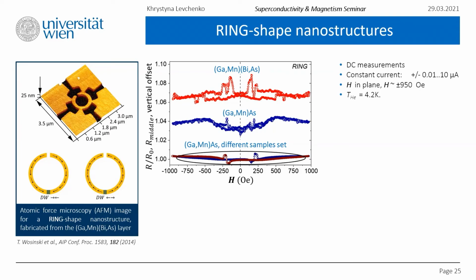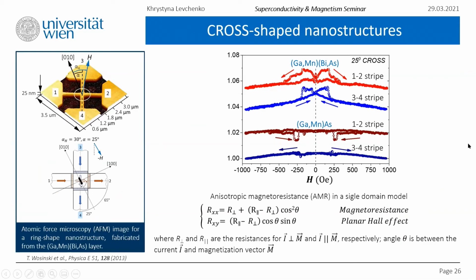So we wanted to have a large difference in the cases of low and high resistance, because the state of low resistance can be set as a 0, and the state of high resistance can be set as a 1. If we are having such a magnetic memory-like structure with such an encoding, obviously we want the difference between the 0 and 1 to be as large as possible. And that is why the increase of the magnitude and coercive fields that comes with the addition of bismuth is so important. What is even more interesting is the dependency of the cross-shaped nanostructures.